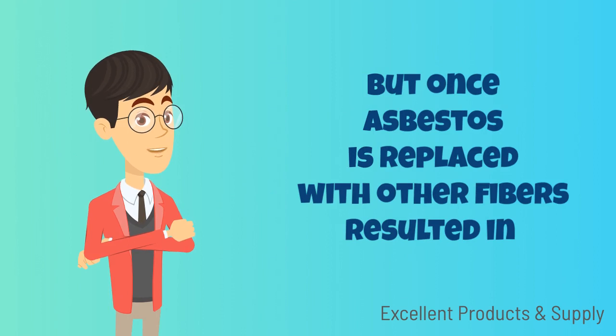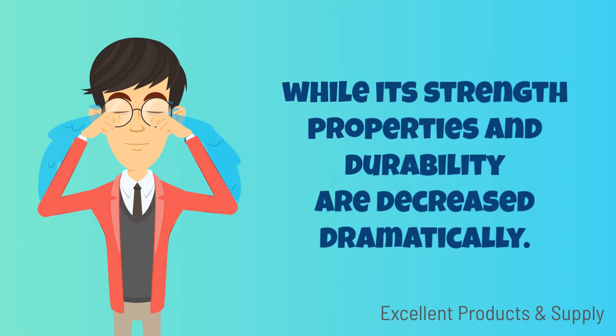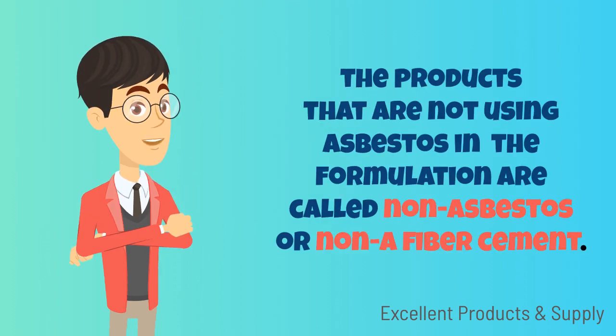However, once asbestos is replaced with other fibers, the cost of fiber cement material is much higher due to higher cost of raw materials, while its strength properties and durability are decreased dramatically. The products that do not use asbestos in their formulation are called non-asbestos, or non-A fiber cement.